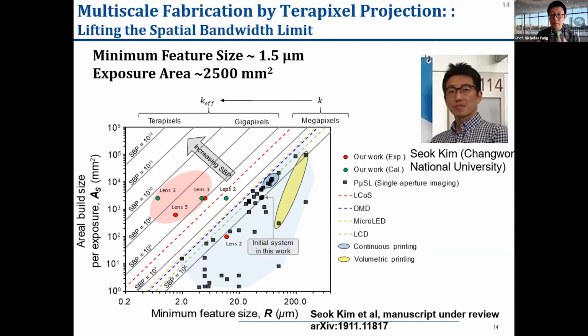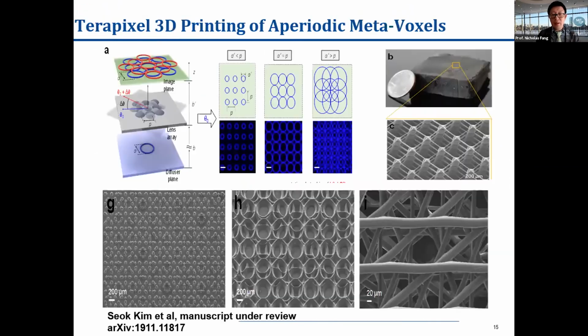So if you want to pursue a fine feature, then you also have to sacrifice the area at which the pattern is being projected. So Professor Seok Kim, who just joined Changwon National University, conceived this idea of using new projection tools so that we can now successfully push the projected pixels from megapixels all the way to terapixels, a 6 order of magnitude improvement in this case, while maintaining the feature size at a few micrometers experimentally. So how did he do that?